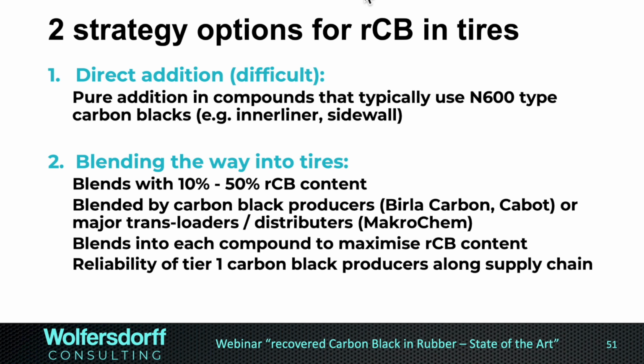The important thing is the blending only works before the pelletization, because the pellet of the recovered carbon black is more heavy than the pellet of the furnace carbon black. And if you just mix the pellets, then on a long bumpy road, it could be that in the big bag or in the silo truck, the recovered carbon black pellets will be underneath and the furnace carbon black pellets will be on top. So really, we need to pelletize the recovered carbon black into the furnace carbon black. The blends into each compound.